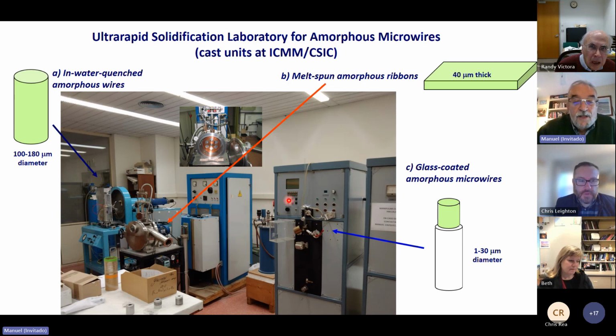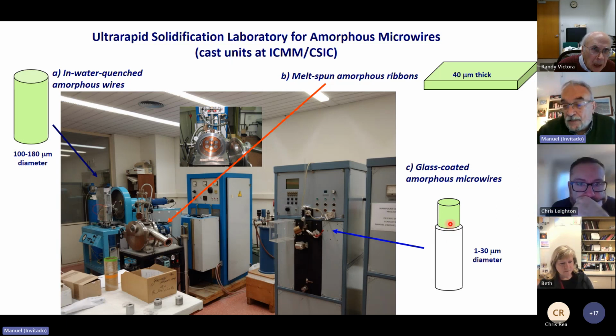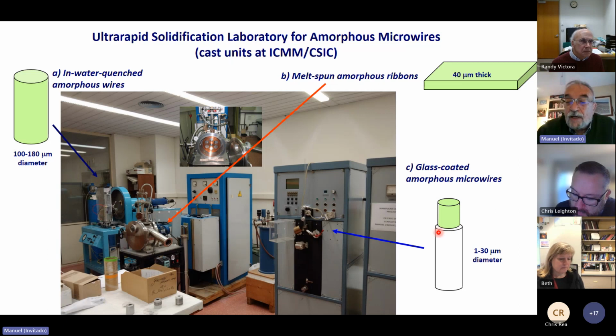of microwires. So I will be talking today about two families of amorphous microwires, those produced by the so-called in-water quenching technique with a diameter roughly between 100 and 180 microns, and particularly the so-called glass-coated amorphous microwires, which consist of an internal core, which is metallic, ferromagnetic, and amorphous structurally, with a diameter of 1 to 30 microns, roughly, and they are coated by a Pyrex insulating coat. This insulating coat provides insulation from corrosion and from the electrical point of view, but also introduces significant mechanical stresses.